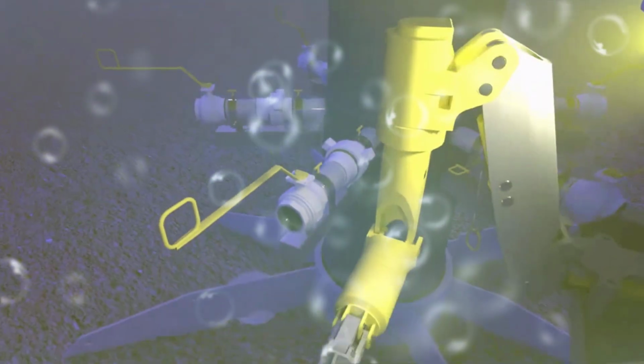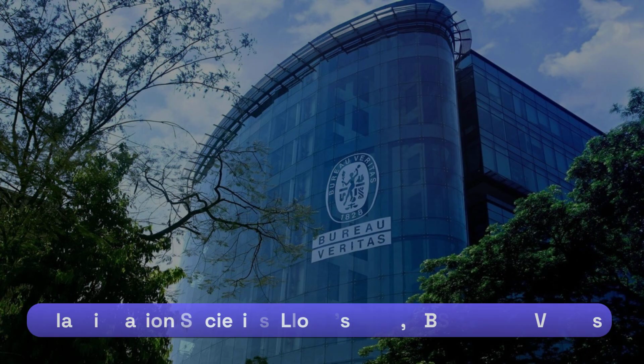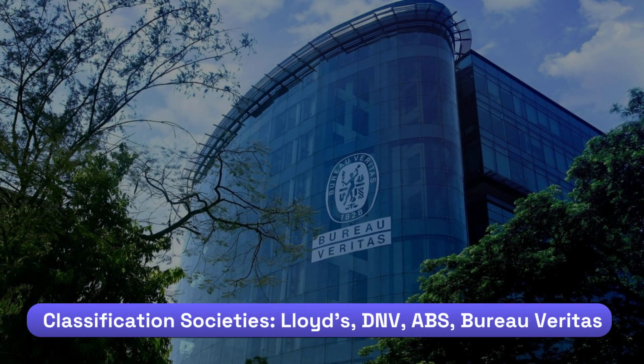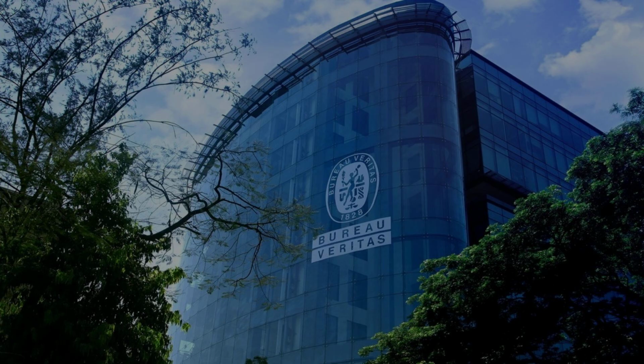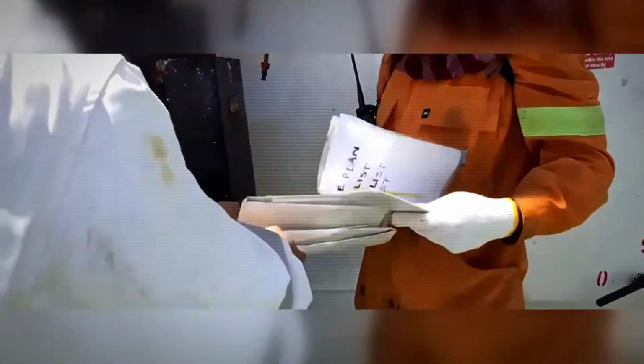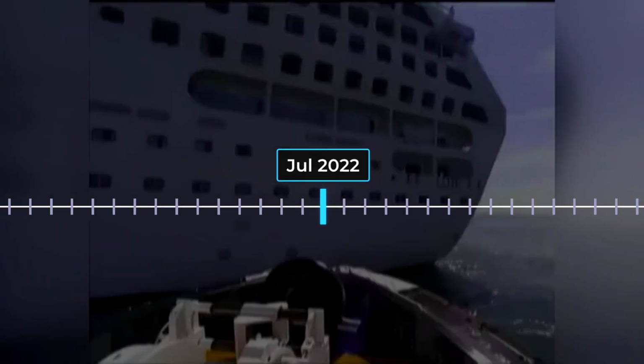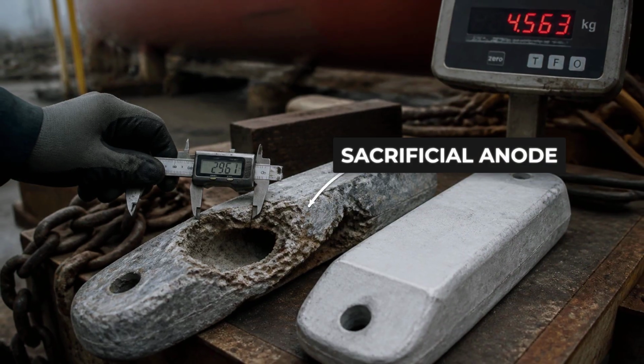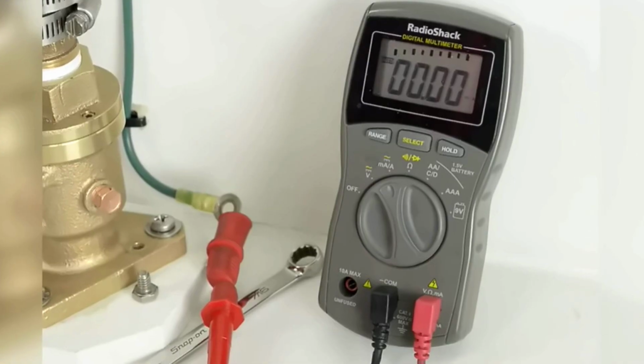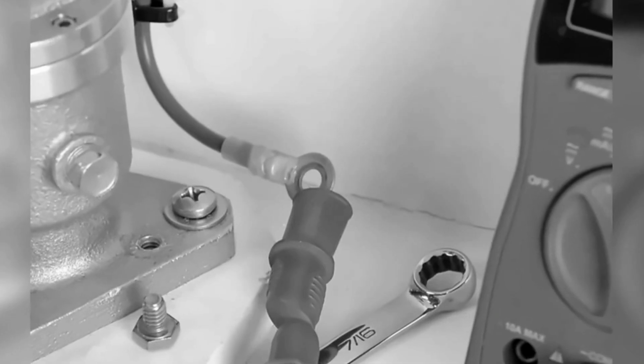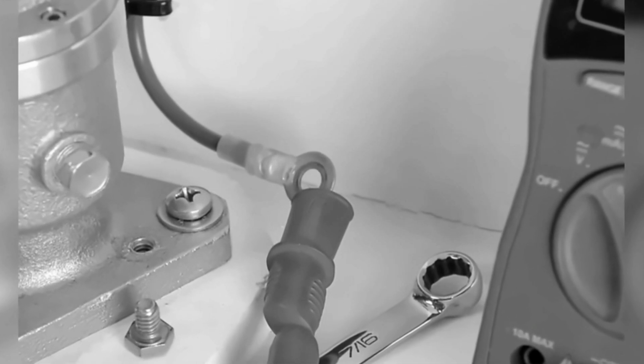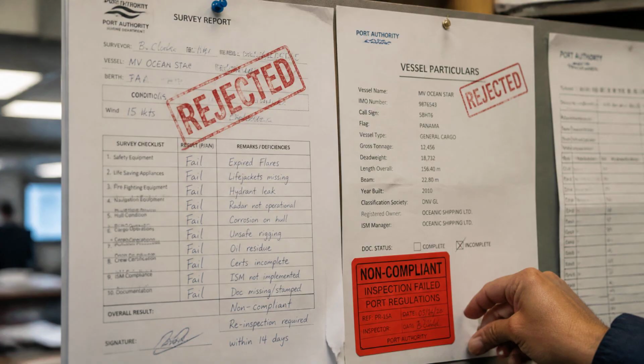The integrity of this underwater defense does not rely on goodwill. It is enforced by international maritime authorities. Classification societies like Lloyd's Register, DNV, ABS, and Bureau Veritas establish the rules that keep these hardware systems operating. Under these regulations, sacrificial anodes must undergo formal inspections on a strict cadence, typically synchronized with the dry docking cycle every 2.5 to 5 years. Once an anode loses half its original mass, its ability to supply a protective electrical current drops significantly, requiring immediate replacement. The rules leave no room for compromise.